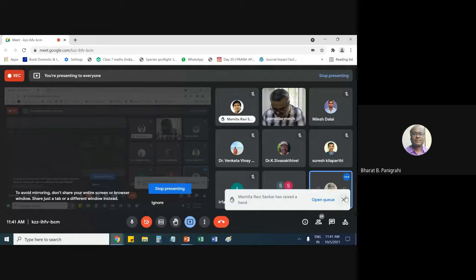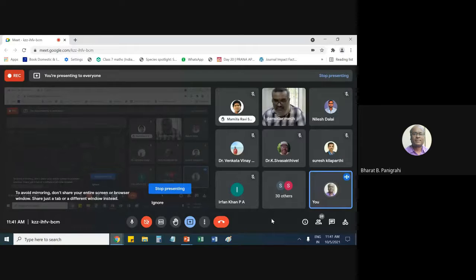Okay, fine. Thank you. So dilatometers come in various ranges and configurations. It all depends on the specification. It comes typically in three forms, based on temperature range. There is a low temperature dilatometer, which can go up to 1100. Another comes with a medium high temperature range, which can go around 1600 to 1700. And there is a third range with ultra high temperature. As you keep increasing the temperature, the cost goes up, and costs start from somewhere around 30 lakhs to 50 lakhs, depending on the specification.